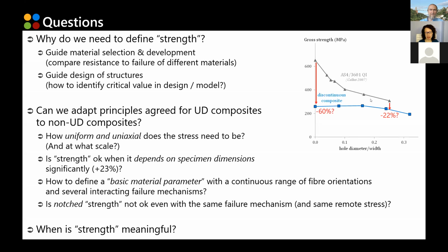So a first question is how uniform and uniaxial does the stress need to be? And at what scale does that need to happen? Do we think that strength is still okay when it depends on specimen dimensions significantly? So you have seen before, just by increasing the width by a factor of 4, you get a decrease of the strength by almost a quarter. Is it still okay in this case?